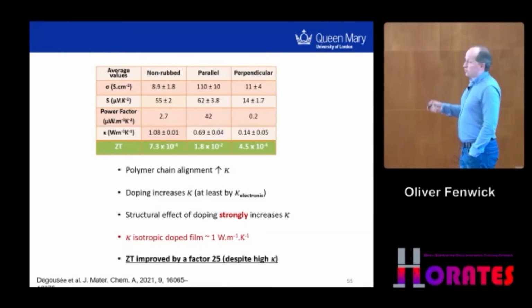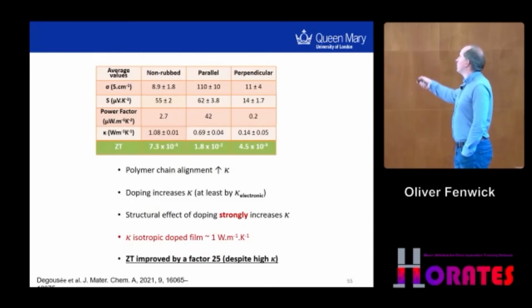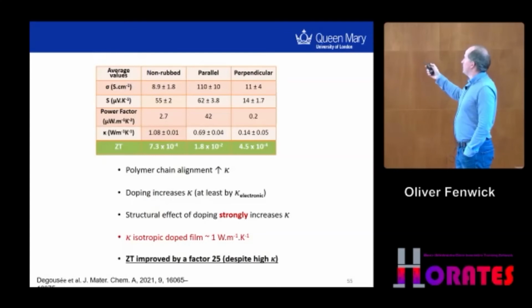The final message is, of course, we had high power factors. We still have a very good enhancement in ZT. It's just slightly less strong than the enhancement in power factor. So a factor of 25 enhancement in ZT between the aligned film and the unrubbed film.